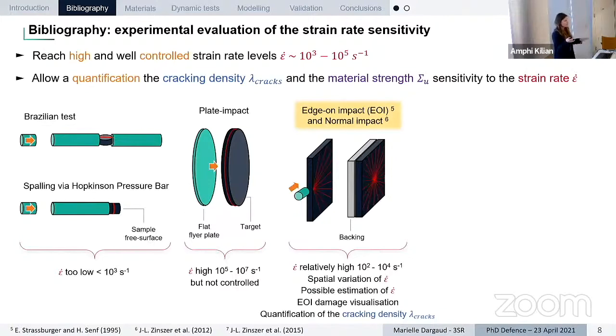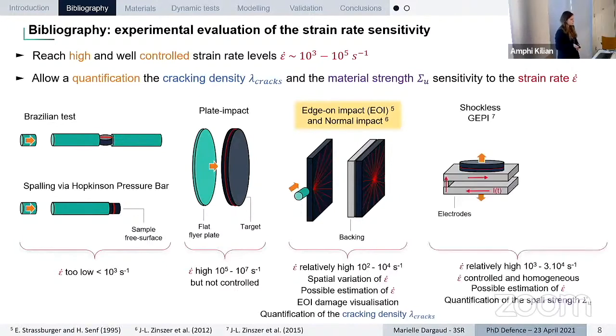And if we look at the type of fragmentation that we would get from these two tests, we have the development of radial crack from the impact point. And this configuration allows to estimate the cracking density in the material. Then, in order to also quantify the strength of the material, there is the GEPI technique, which can induce a spall failure in the ceramic at a controlled loading rate in the failure area. This technique is very specific, so we induce an impulse current in electrodes, which generate a magnetic pressure, causing the failure in the material. However, this technique presents some main limitation. It's difficult to set up, it's very expensive.